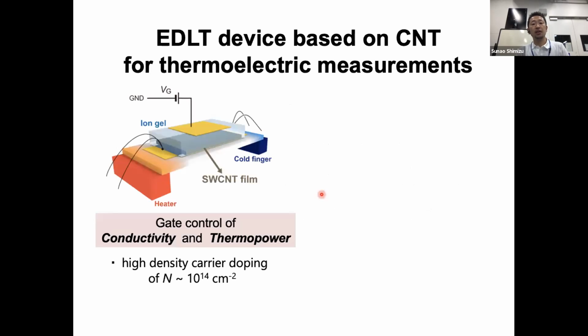Here, we fabricated an electric double layer transistor device based on carbon nanotubes for thermoelectric measurements. This is the schematic picture of the carbon nanotube transistor device. This is the glass substrate, and we put a carbon nanotube thin film, and we put ion gel or ionic liquid to cover the carbon nanotube thin film here. And also we put a gate electrode on top of it. By changing the gate voltage here, we can control the carrier density of the carbon nanotubes.